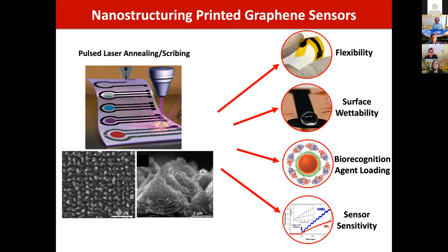And that laser converts it to make it electrically conductive, but we also can tune the properties of that laser that hits that graphene to make these really interesting nano and microstructures on the surface. And that's what you see here in these scanning electron micrograph images, where you see these pyramid type structures or these fins coming off of that surface in the micro and nanoscale.